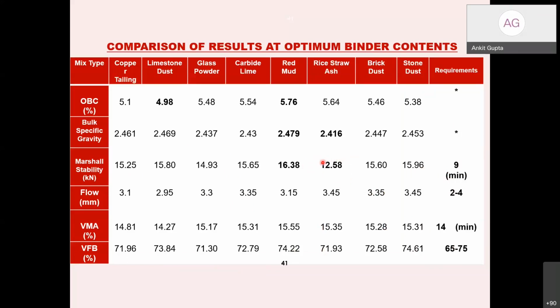The minimum is for the rice straw ash, which is an agricultural waste, which has very fine fillers. The very finer fillers were there, and which has the very least specific gravity. But the highest specific gravity, that is the red mud, is getting the highest Marshall stability also. So one of the strongest mixes we are getting is from the red mud.